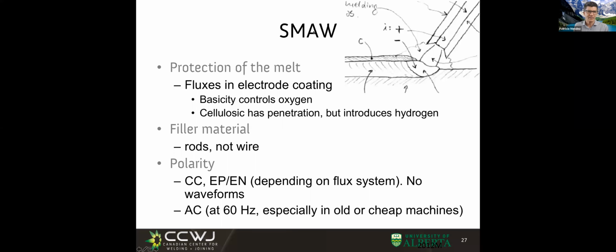One of those, for example, is the cellulosic electrodes. Cellulose, if you remember, is essentially paper. That's what makes paper. And originally, they invented the cellulosic electrodes by wrapping the electrodes in newspapers. And what happens when the newspaper, or in this case the cellulosic fluxes, burn out? They generate CO2. It's a shielding gas, much like in MIG we use CO2, right? But because cellulose is an organic material, it also has hydrogen, which makes the arc a lot narrower and more concentrated. So these cellulosic electrodes have a shielding gas generated by the CO2, and a very powerful, concentrated arc because of the hydrogen.